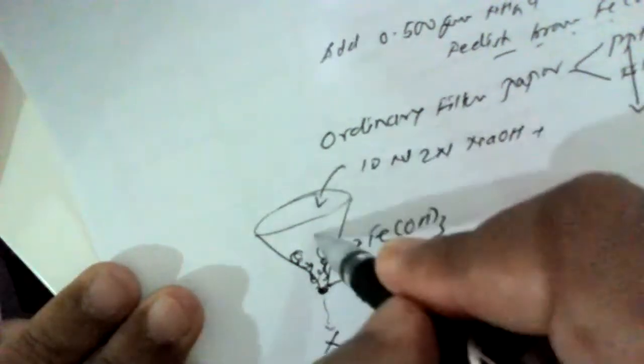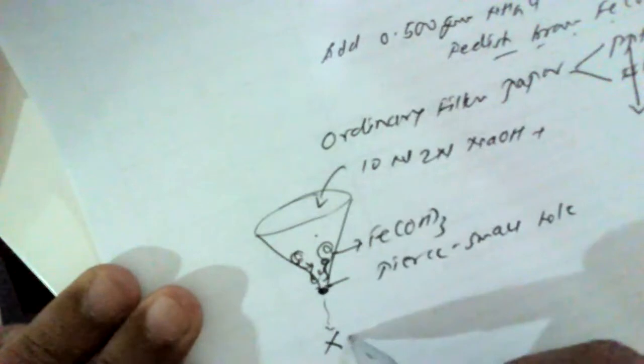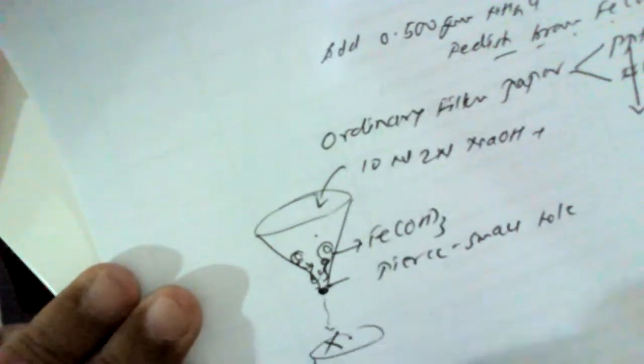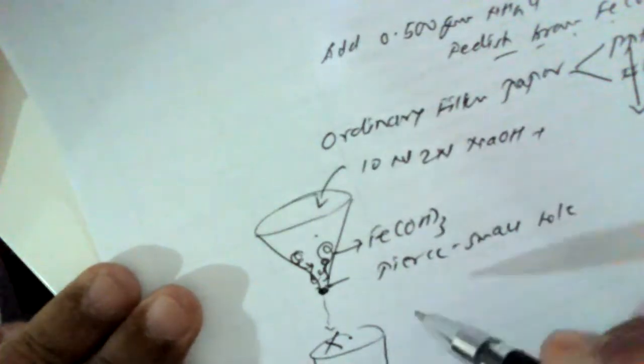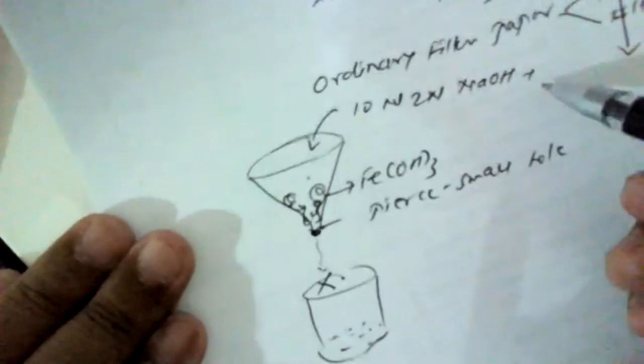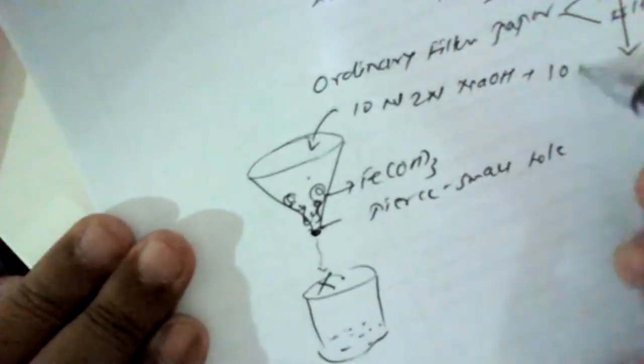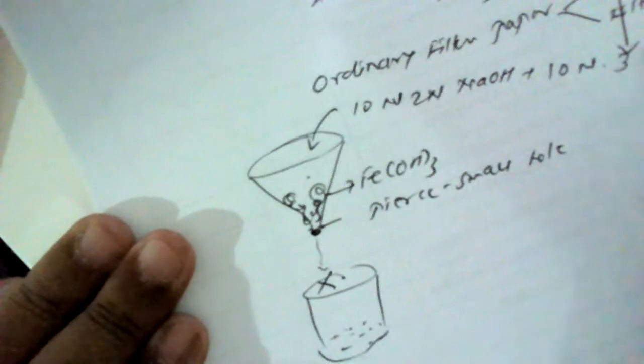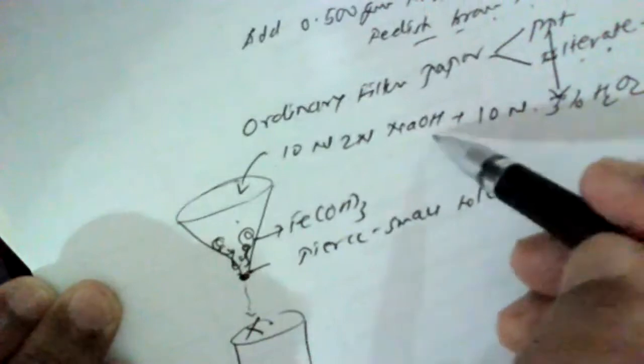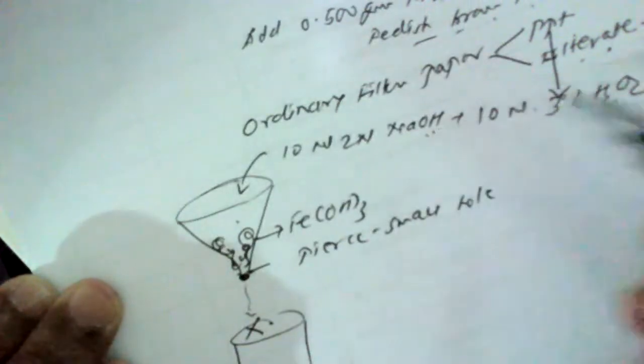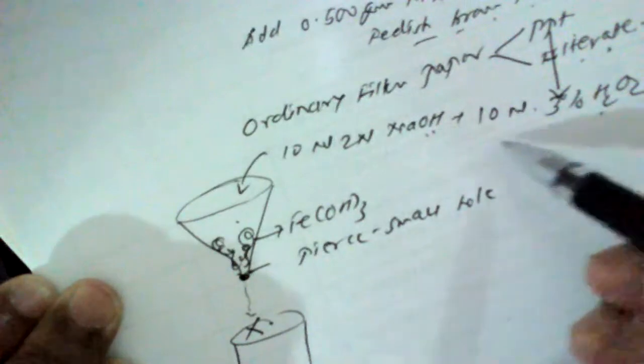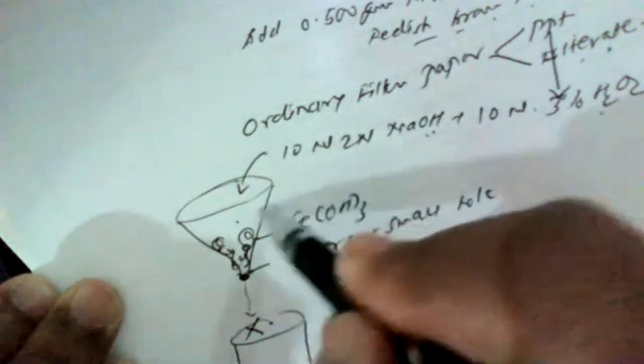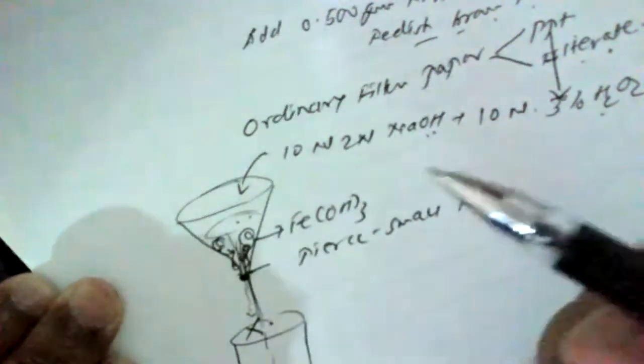After adding this NaOH solution, it is to be collected in a separate beaker. Here, we have to keep a beaker to receive whatever content is obtained by adding NaOH solution. Then, after adding NaOH, we have to add again 10 ml of 3% solution of hydrogen peroxide. First of all, we add NaOH solution, then we add hydrogen peroxide solution, 10 ml of 3% solution, in a circular fashion so as to collect all the precipitate in a beaker.